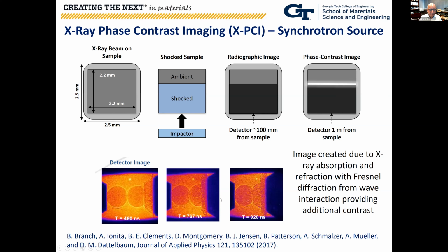Okay, and these are examples of detector images of two silica particles. As they have been pushed towards each other, you can see the cracking that is generated in one of the particles here. And in this image, you can see cracking propagating in both of the particles. Due to cracking, there are free surfaces that open up, which are low density regions, and that's the reason you're getting that additional contrast.